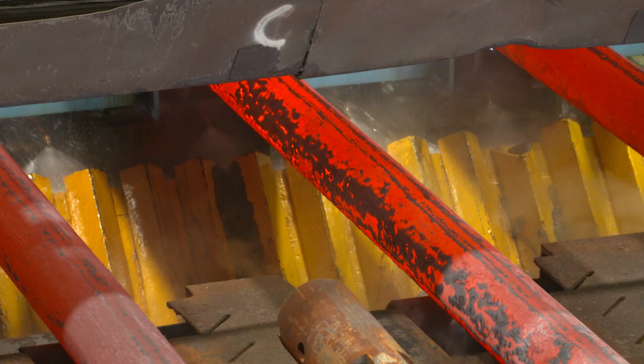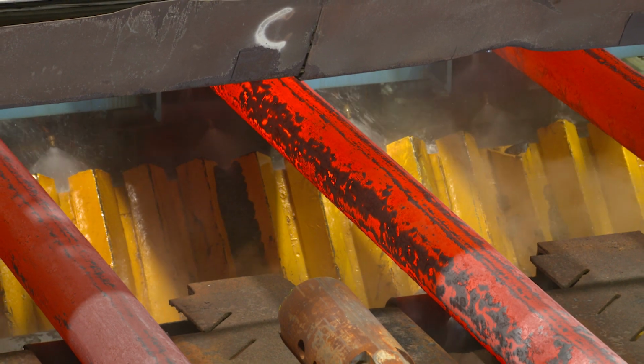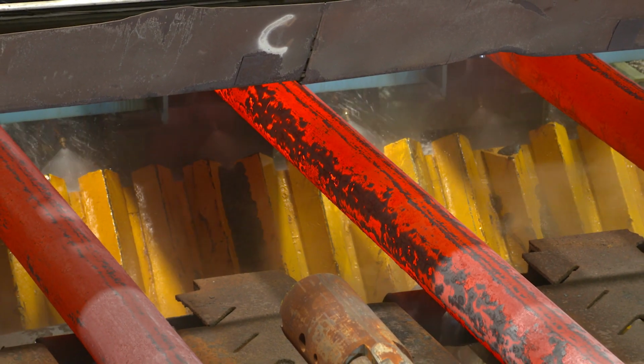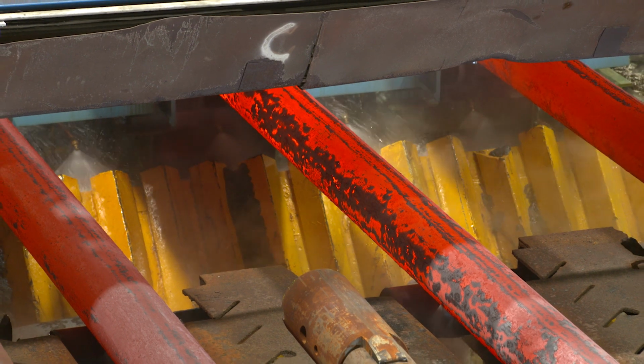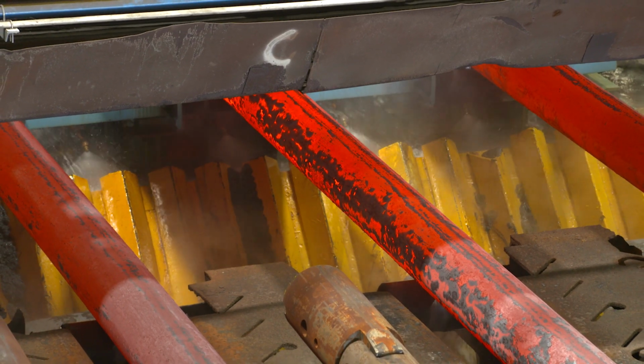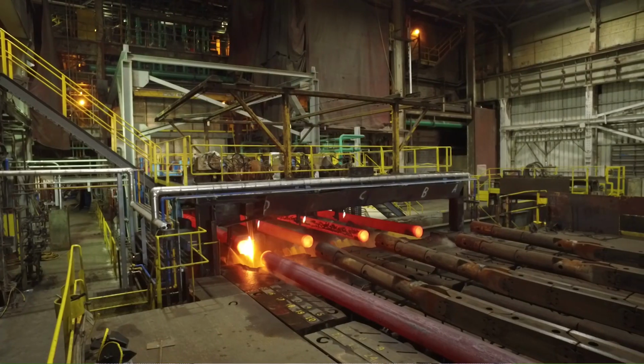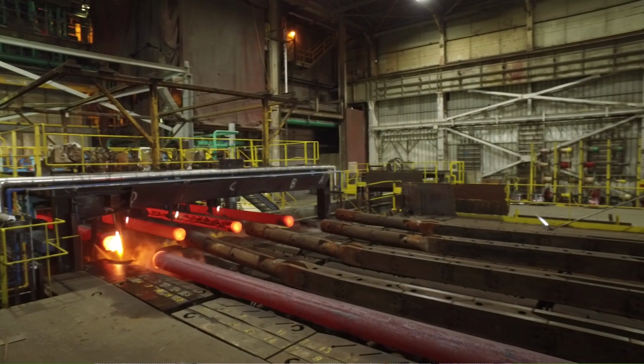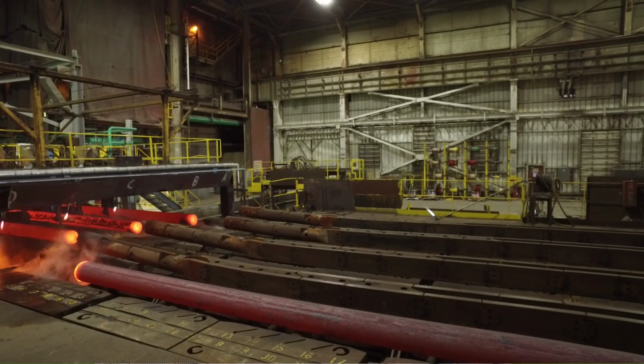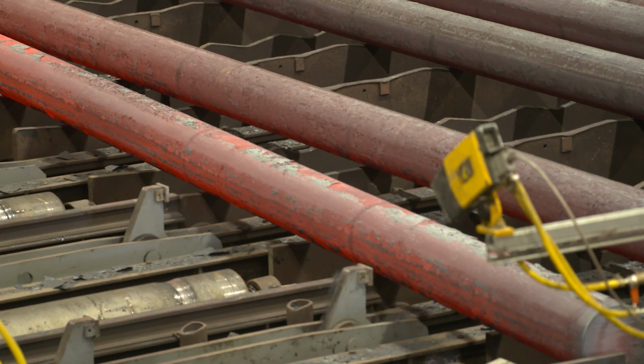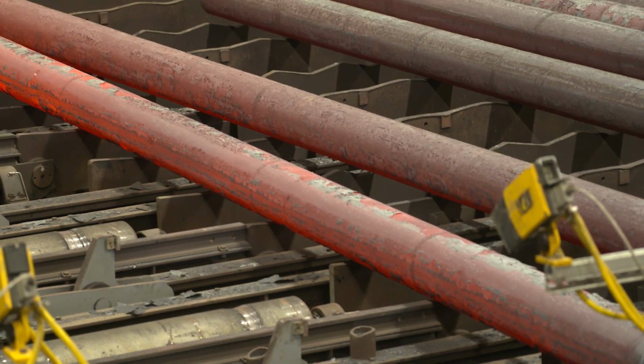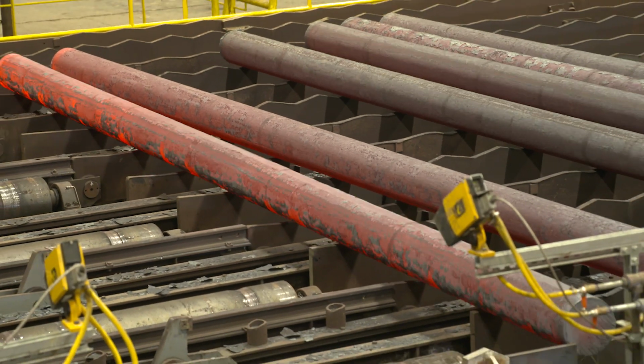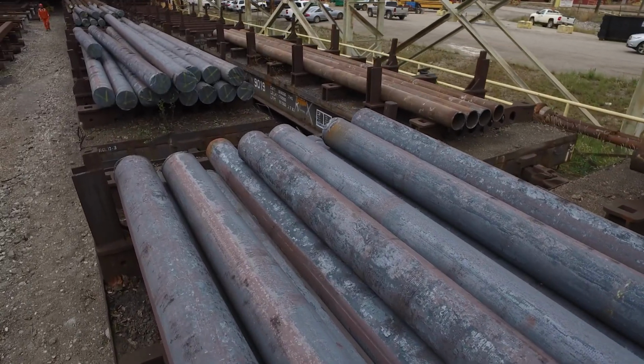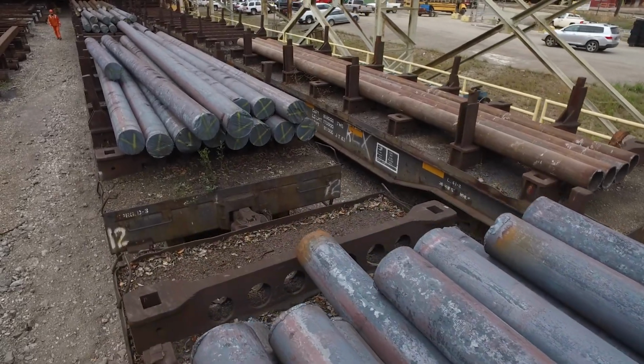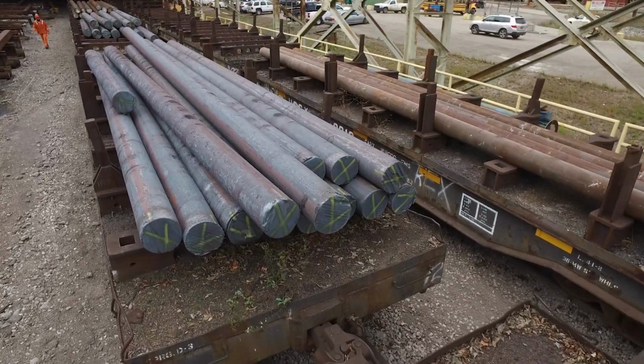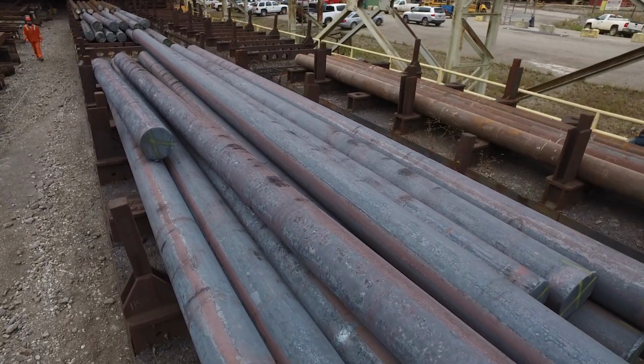The molten steel goes into a water-cooled copper mold and is then extracted through a spray chamber that strategically sprays water and carefully cools the newly formed shape based on chemistry and speed. The strand is then straightened and cut into customer-desired lengths. Each round is inspected, tagged, and sent for cooling prior to being loaded onto a rail car. The rail cars could go to one of our facilities where they would be made into seamless pipe, or they could be sold as rounds to an outside party for other applications.